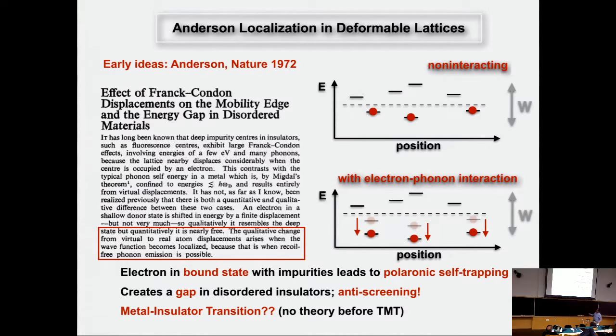He had language for this, it's called the Franck-Condon principle, but basically he said that if you have bound states like this due to disorder, and you turn on electron-phonon coupling, those that are occupied will come down and the other ones won't. And the net result of this is that you will tend to open a gap. This is what Anderson said. And it's very easy to show that if you have very strong binding in any model of electron-phonon coupling, you'll see that this will immediately happen.